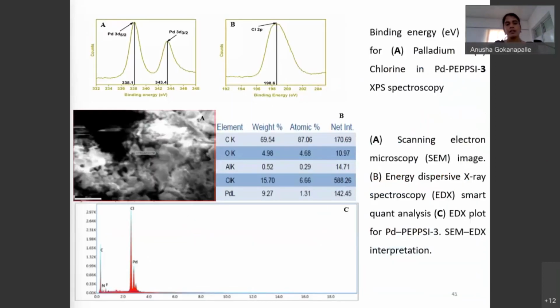This is the XPS spectra of palladium PEPPSI 3. These two peaks show the binding energy at 338 and 343 that are related to palladium, and this is corresponding to chlorine at 196. This is the EDAX spectroscopy. It shows the presence of palladium and chlorine in the synthesized palladium PEPPSI complexes.